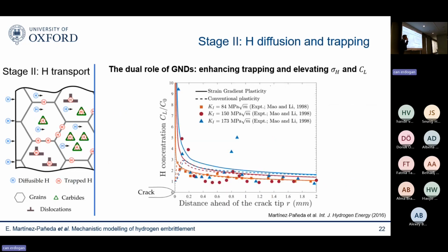And in fact, we have seen when we run simulations combining these coupled chemo-mechanical models that account for the GND effects, for these strain gradient plasticity effects, this is the only way that we can get a good agreement with experiments. It's difficult to measure hydrogen concentration ahead of the crack, but some people have done it. And you can see here that only by accounting for these GND effects, we're able to capture these very high hydrogen concentrations that experiments predict near crack tips.